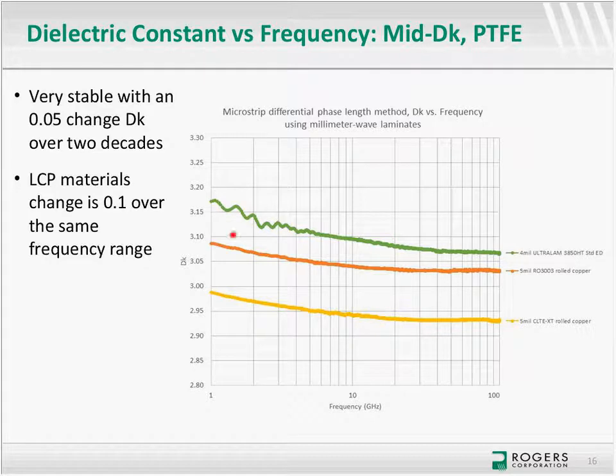You can see the change is slightly higher as you move away from the pure resin, PTFE, and some other mixed materials. You're going from maybe 0.05 to 0.1 in overall change in dielectric constant. Again, in these applications, we'll find that at 40 gigahertz, you're staying mainly around 40 plus or minus a couple of gigahertz. So you'll see within that it's a very, very flat value.